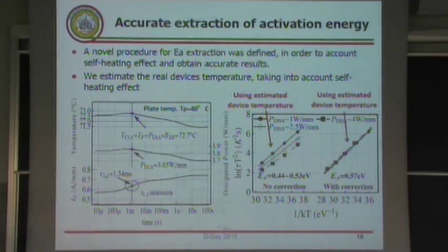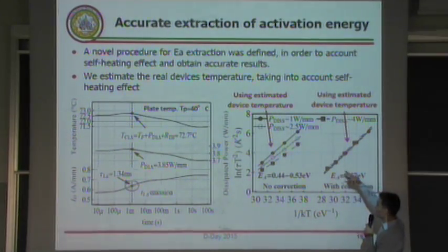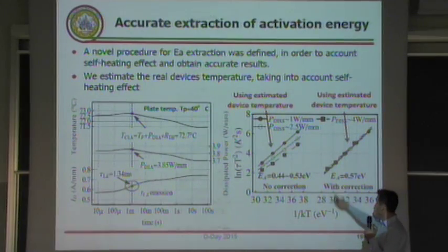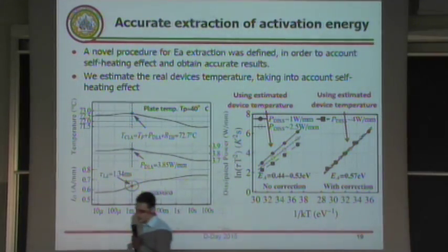However, we developed a technique to do an accurate extraction of the activation energy using the drain current transient, and this technique takes into account the self-heating caused by the dissipated power. So basically, we measure the dissipated power during the measurement, and we estimate the real temperature of the junction of the device. In this way, we were able to correct the points and extract a unique Arrhenius plot even at different dissipated power. You can see that after the correction, here on the right, the Arrhenius plots extracted at different dissipated power are nicely overlapping, and also we obtain a unique value of the activation energy. So in this way, we are able to do a correct characterization of the traps.